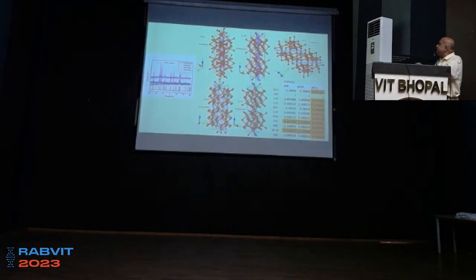Okay. So we took the intensity ratios and normalized them with the 104, which is a neutral axis plane, and found that the only two changes that are happening very drastically and consistently are these two, the 21410 and the 10110 plane. This is a neutral plane, but this one is an oxygen termination plane, which is a negative termination. Okay, you can see this 214 is somewhere here. Yes. So this is the oxygen termination plane. So if this plane is on the termination side, then we'll have a negative surface. Now the intensity of this plane is going down gradually. So that means the contribution from the negative surface is going down.